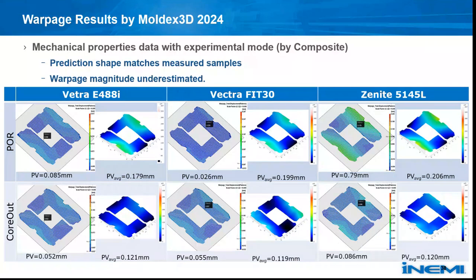Next page. So next we talk about the circuit validation results. We first examine the general method with input by composite. The results show the warpage at room temperature of 2 circuit models and the 3 LCP grades. The left plot of each set is the predicted surface shape, and the right plot is the measured surface shape from the thermal deformation measurement. We can see the predicted surface shape matches the measured sample in all the sets, but we also find that the magnitude is underestimated compared to the measured value. Next.